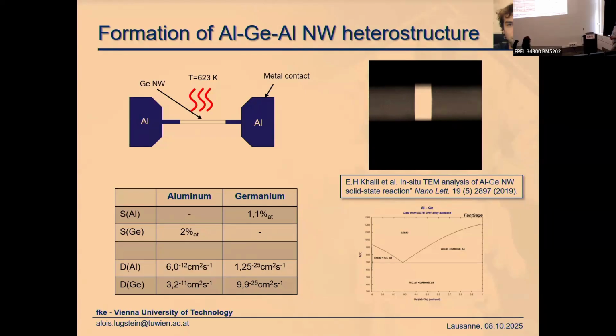So it's not possible to make 100 by 100 micrometers? This will be polycrystalline. But what happens if you have multiple disconnections? Exactly, that's what we do. We make several of these channels, and you collectively end up with the total current. Exactly.